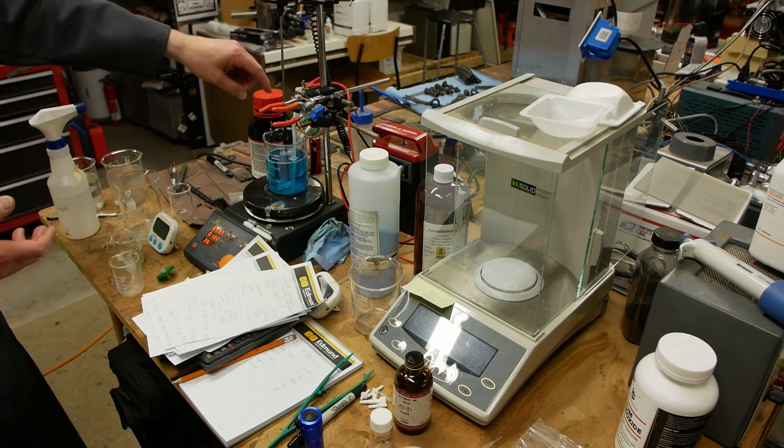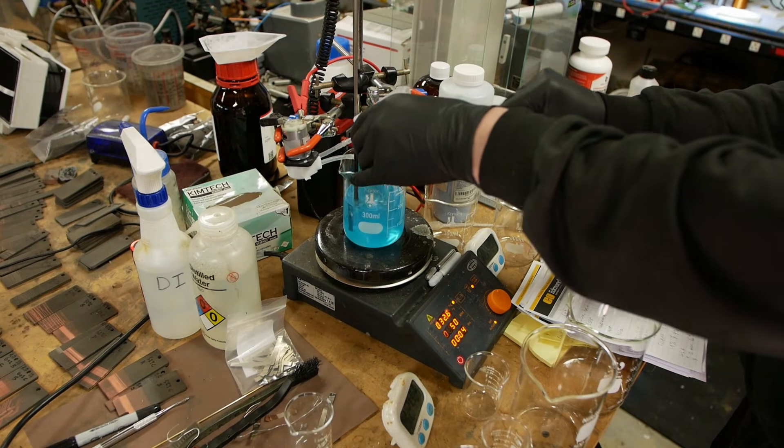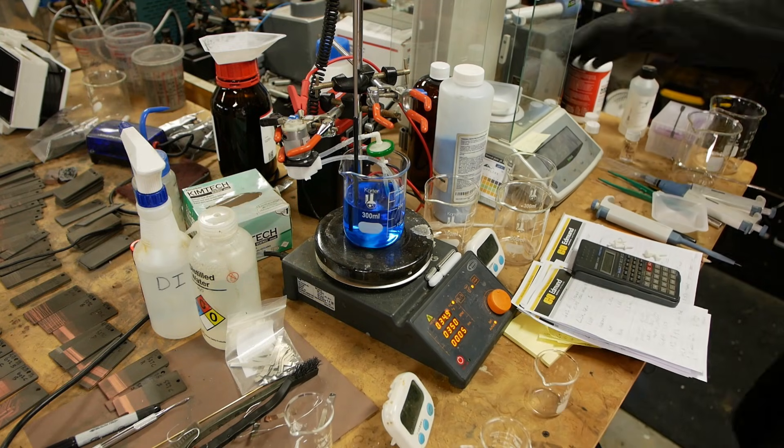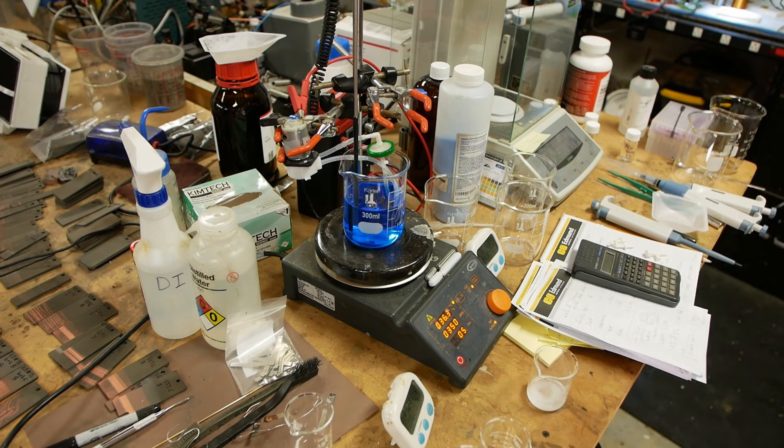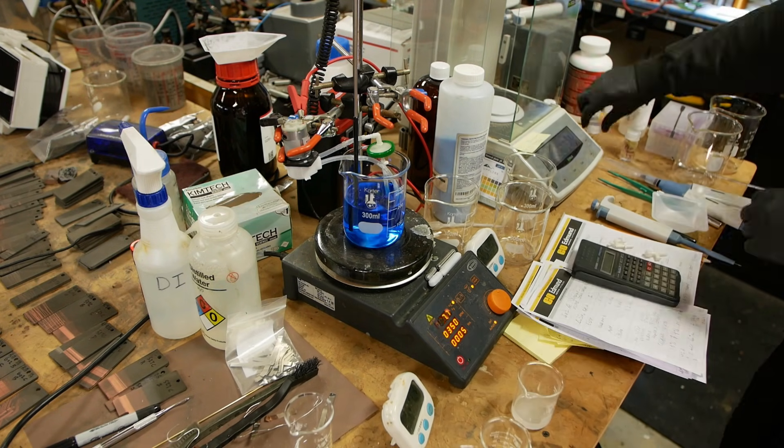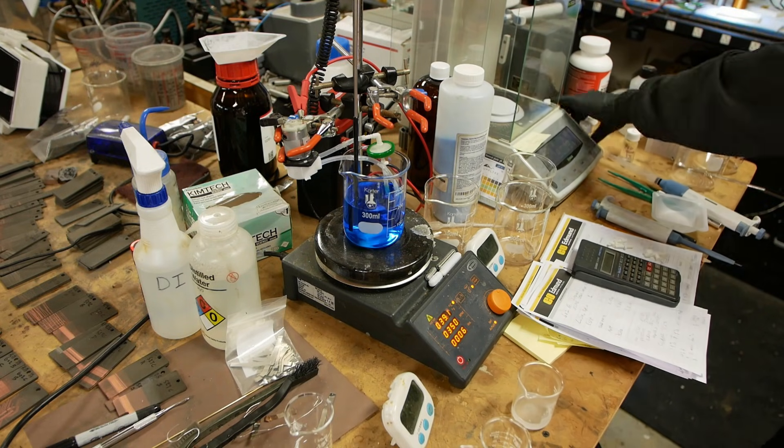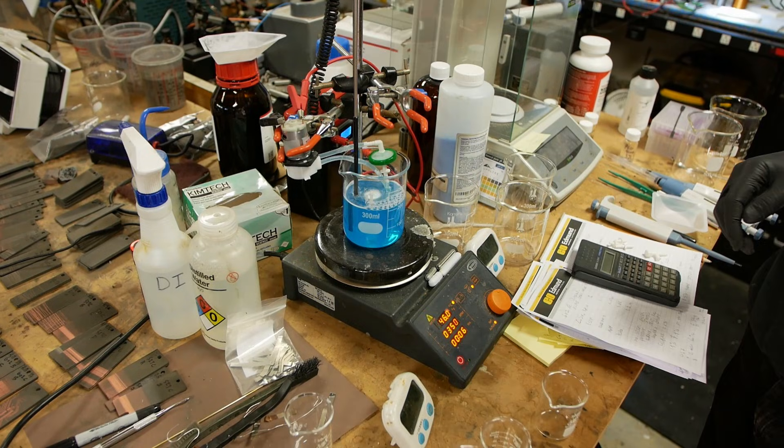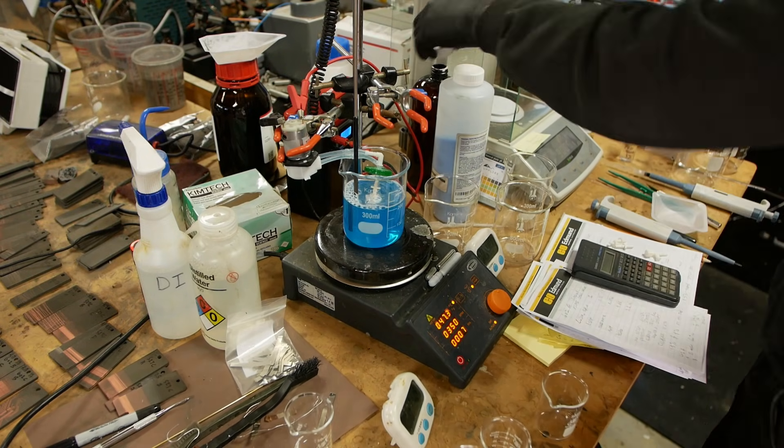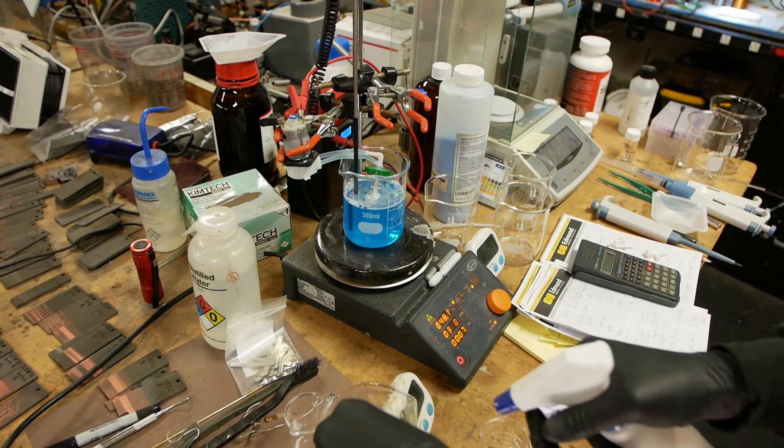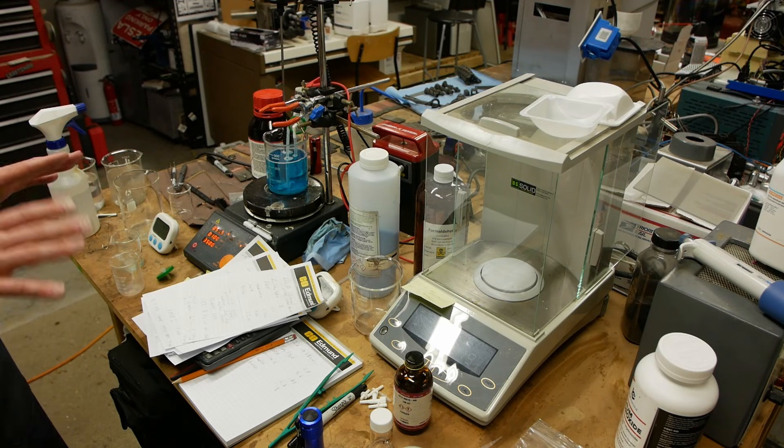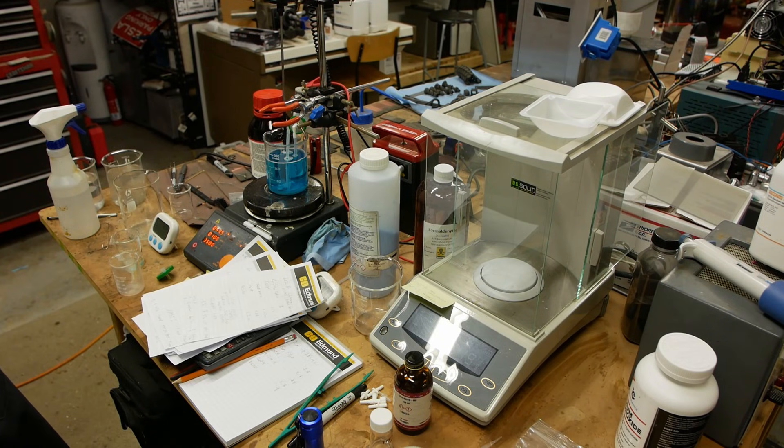So another little remedial function that I came up with is filtering the solution to make sure that there's no dust particles in there. So I came up with this tiny little peristaltic pump and a syringe filter, and that filters at maybe half a micron or something to make sure that all the dust in the solution is out. So stirring, filtering, temperature control, the right chemicals, it is in fact repeatable, and I feel like I got the process under control.